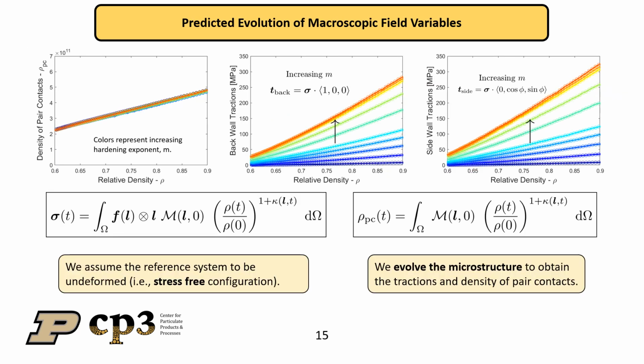We can subsequently also predict the evolution of macroscopic field variables, which in this case would be the density of pair contacts, rho PC, the backwall tractions, which is the projection of the stress in the loading direction, and then the sidewall tractions, which is the projection of the stress tensor in the lateral cylindrical direction. And what we can see is that we get remarkable predictability of this model, assuming that we know the parameters of M. And we can then utilize the parameterization of M in the form of the evolution law to update the macroscopic field variables. And one key aspect is that we utilize a stress-free configuration as our reference configuration and update relative to that.